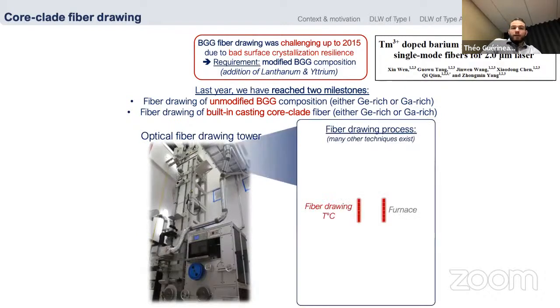There are several types of technique that we can use to fiber draw our glasses, but in this case, one of the most used, I would say. We insert our glass preform in a preheated furnace above the Tg to get the glass softer again. Then we can pull the glass and draw the preform into fiber.